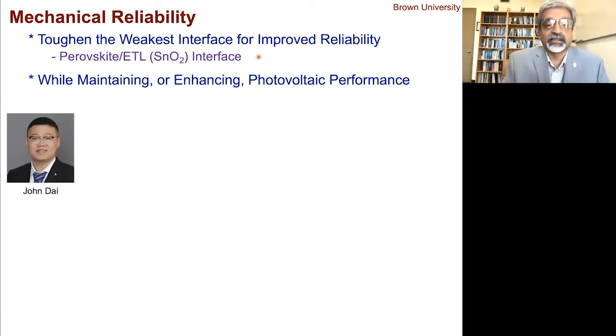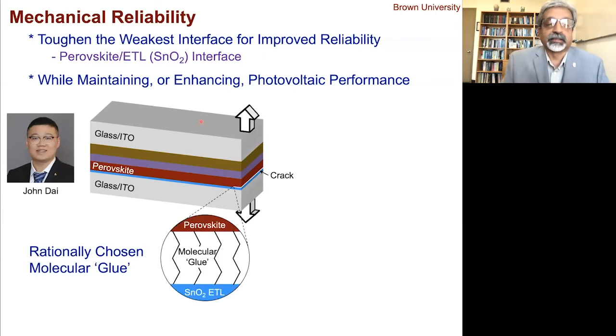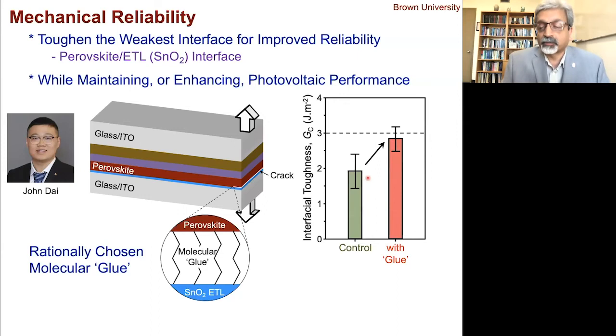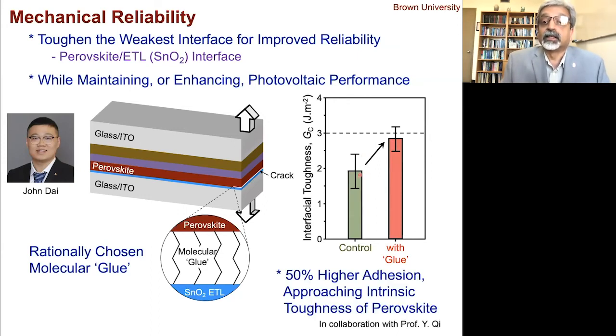And this is the work of my PhD student, John Dai. And this is what he has done. So this is a perovskite thin film, and this is the ETL. And basically, we have used a molecular glue here. Again, I cannot tell you all the details here, but this molecular glue improves the adhesion of this weak interface, right? And he measures the toughness by applying load. And what he finds is that there's about 50% increase in toughness going from a control without the glue to with the glue, approaching the single crystal value, or the toughness value of the perovskite itself. So it's really an amazing achievement. And this work is going to appear in Science in 2 or 3 weeks.